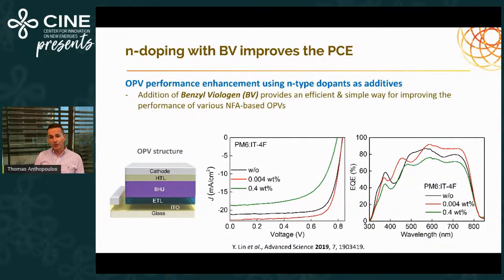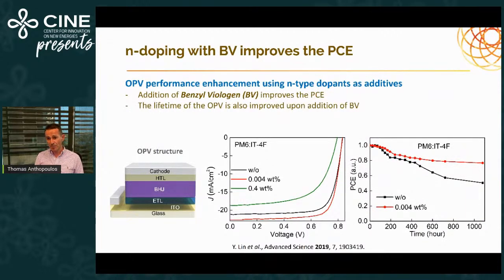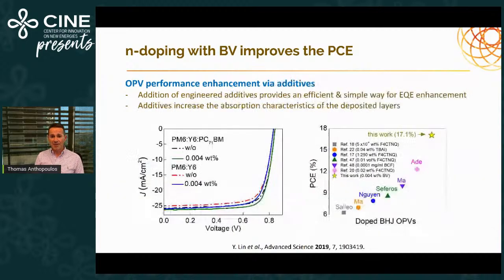Indeed, when we made the devices, we realized that minute amounts of this dopant present in the bulk heterojunction, 0.004 weight percent, can increase the short circuit current quite a lot, and essentially lead to dramatic changes in the EQE spectral shape. You see different features being enhanced because of the changes in the optical properties of that bulk heterojunction layer. And of course, the combined effect of better electron transporting, which is also evidenced from our data, and the improved quality of the bulk heterojunction, potentially phase separation of the donor and acceptor components, led to these very interesting devices, which are more stable in terms of operational stability, but much more efficient.